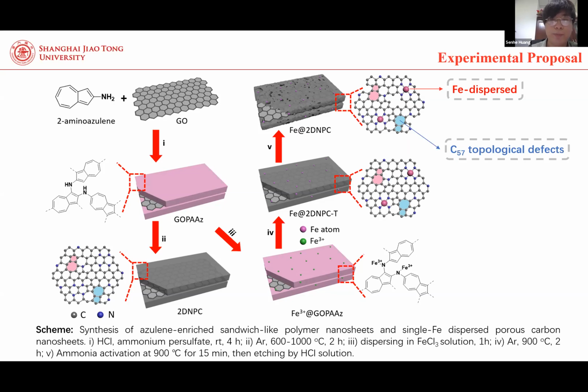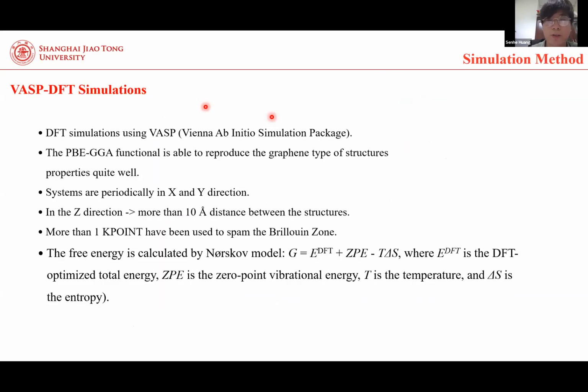We performed DFT simulation using VASP. The PBE-GGA functional is able to reproduce the properties of graphene-type structures quite well. Systems are periodic in the X and Y directions. In the Z direction, there is more than 10 angstrom distance between the structures. More than one k-point has been used. In order to quickly and easily investigate the effects of the defects and the dispersed metal sites on catalytic performance, we adopt the Nørskov method to study the free energy of each species. Besides, we also studied the electronic properties of the catalysts.